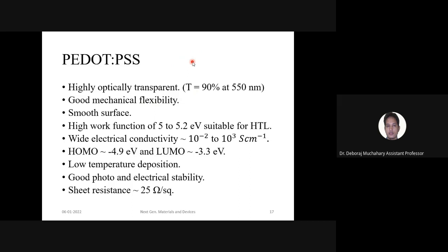Now if you have a rough surface, that means the termination of this crystal structure is rough, so your recombination will be high, and as the surface recombination is high, the device performance will be degraded again. So it is highly related. This PEDOT:PSS has a smooth surface also. No doubt it depends on the fabrication conditions, different growing conditions and all this. But on average we can say that the surface of PEDOT:PSS is smooth, and that smooth surface helps us to design the solar cell. So that is another advantage of PEDOT:PSS.